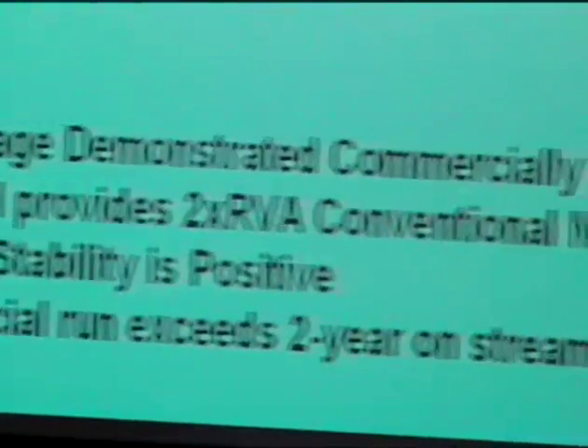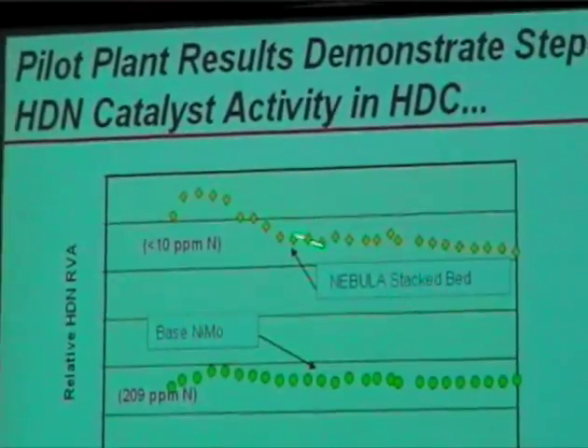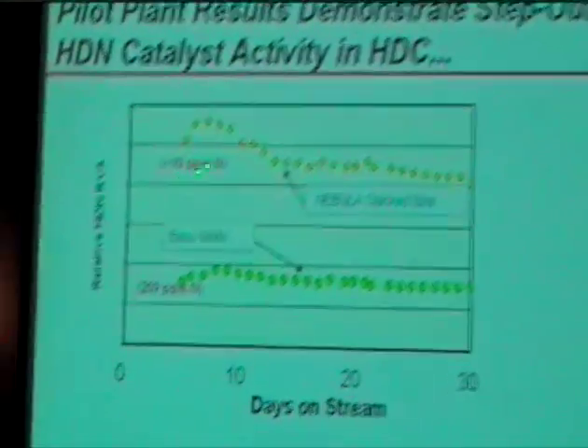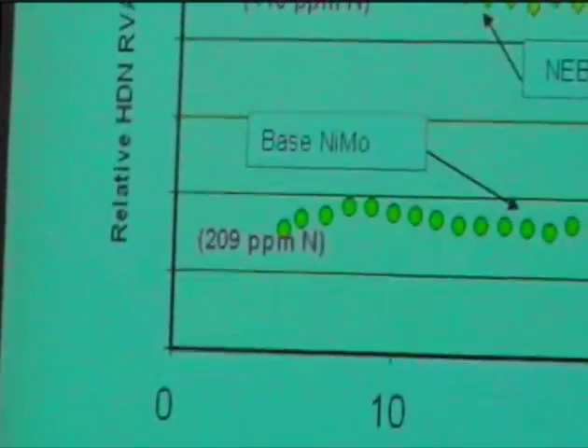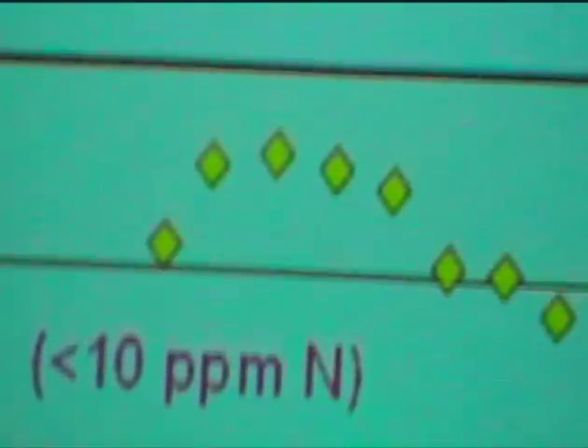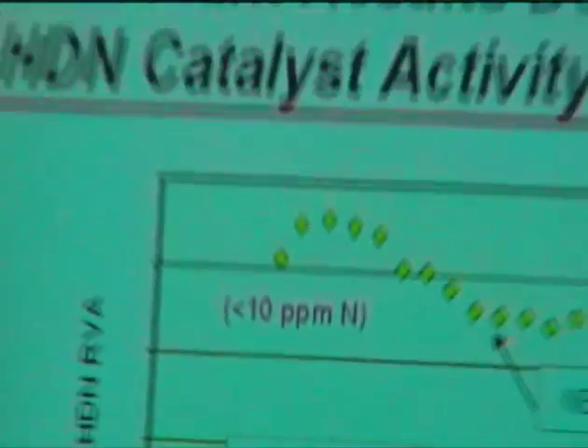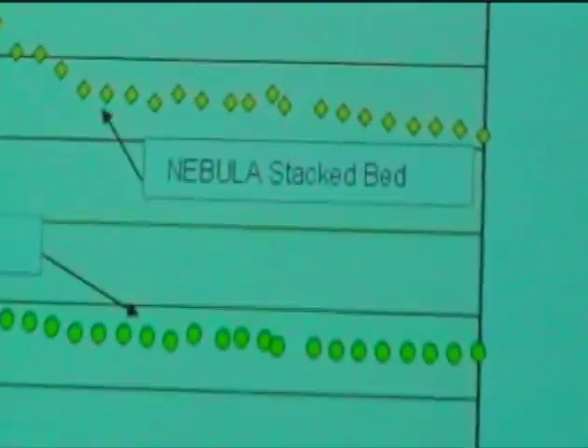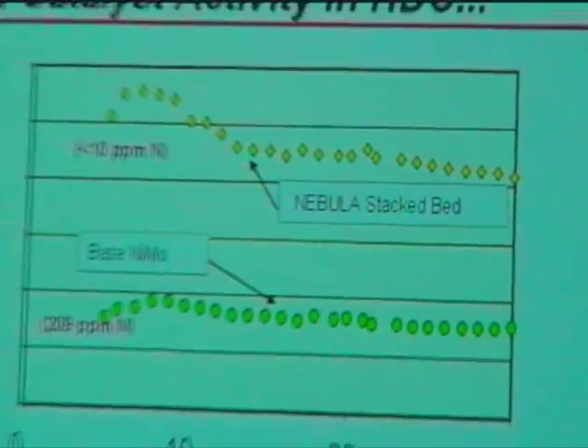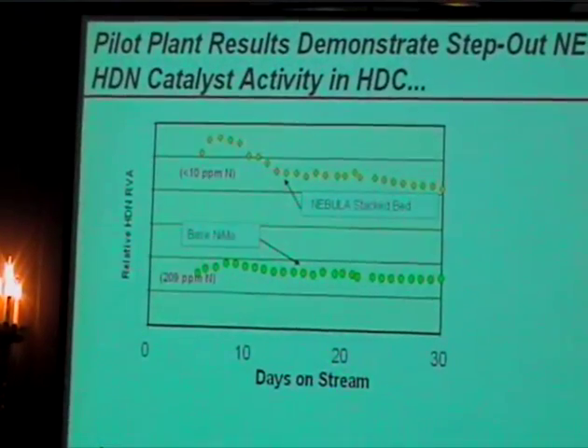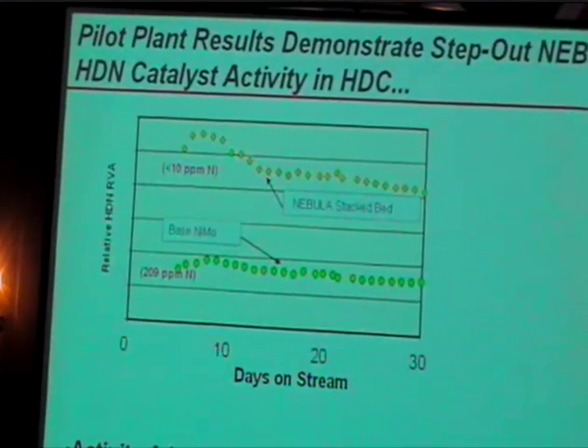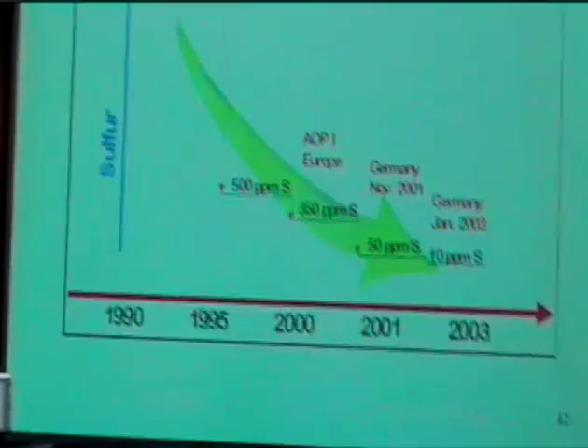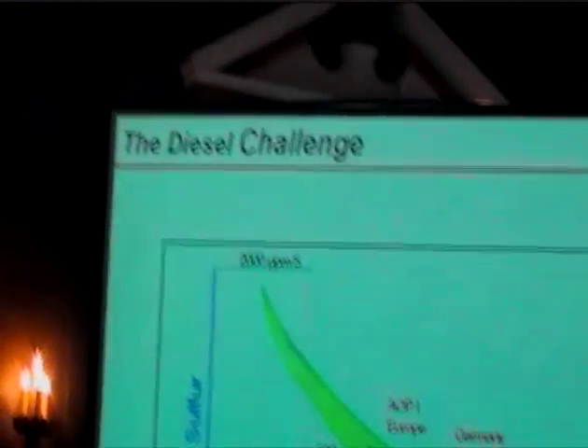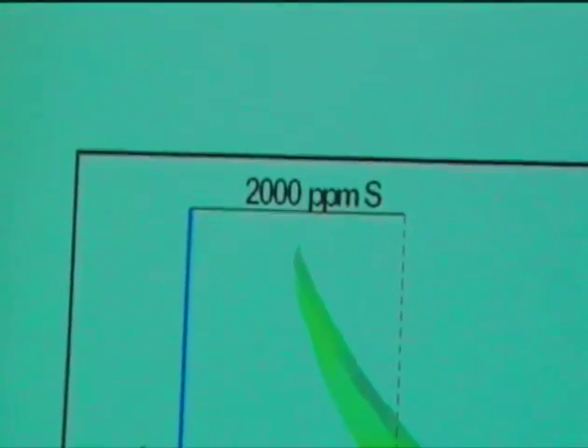And you can see here, it's a pilot plant case comparing a base nickel moly supported catalyst versus a stacked bed using a partial charge of Nebula. And here you can get the nitrogen down in the hydrocracking pretreatment, you try and get the nitrogen down before it sees the zeolite catalyst. And you see how effectively you can do it and how stable it is. So in this particular situation, we were able to get to twice the relative volume activity with even a partial fill. And some of these you can see are already two years time on stream. So there were applications in hydrocracking pretreat, particularly for LCCO.